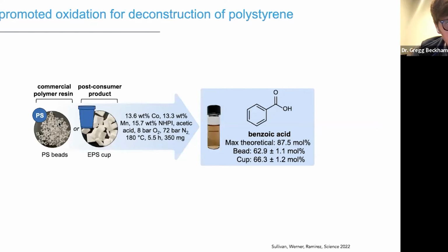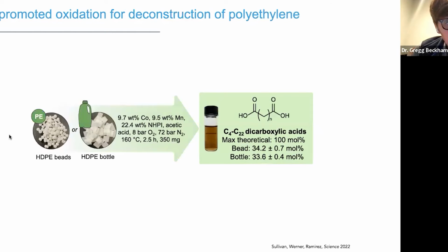And so in all of these cases, I'm going to show you we purchased commercial standards, as well as we went to the grocery store across the street and we bought styrofoam cups. This is for polystyrene. This is in acetic acid, 8-bar oxygen, 5.5 hours, and we can obtain around 66% yield of benzoic acid. We do the same thing for polyethylene, in this case HDPE.